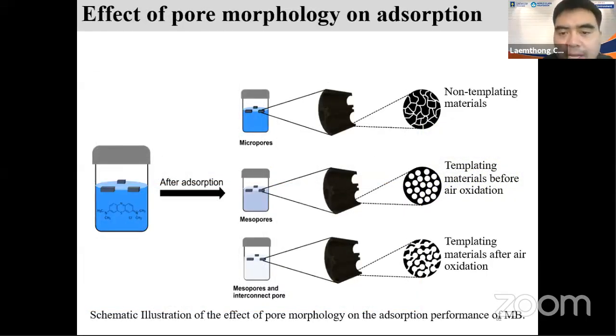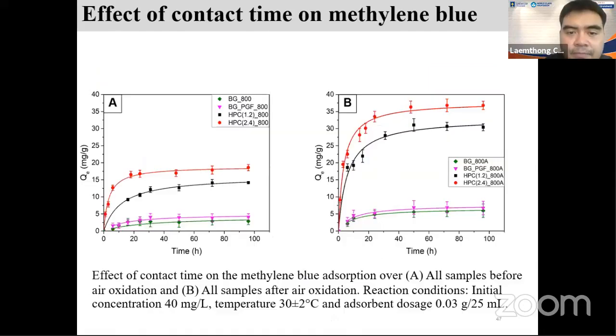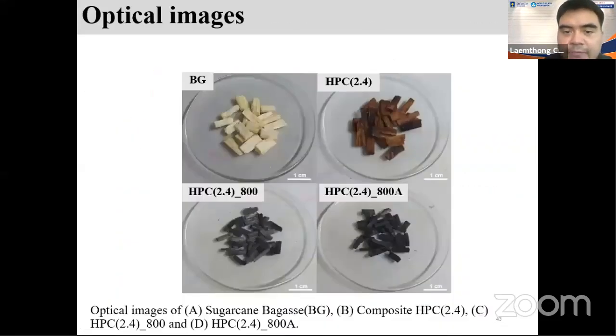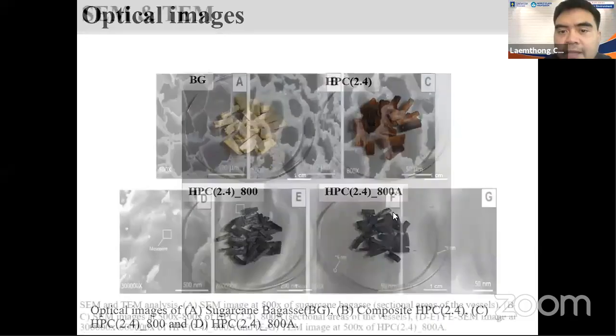And of course, not only this one; we talk about magnetic sorbents, and how could you get the magnetic property into this one? It's quite simple. During the coating process, you can add the iron particles into that already. That means you can put an iron starting material like iron 3 plus into your system. After this, you have to coat it with the resorcinol-formaldehyde coating, right? During the coating, you can incorporate the iron in this step. So after calcination, the carbon will have the magnetic property as well.